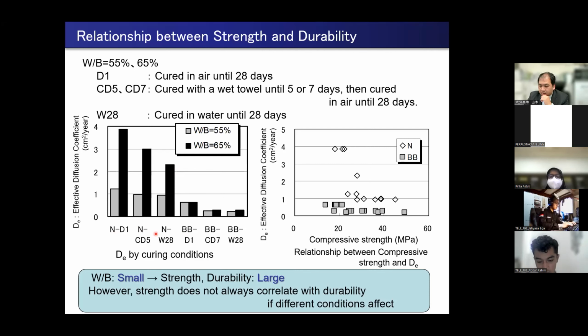And here, BB means blast furnace slag cement. Blast furnace slag cement was used, and the durability shows high durability. But even in this condition, the curing condition affects the quality of concrete. In other words, the durability is different. If wet curing is chosen, then the concrete becomes highly durable. And this affects the compressive strength also.